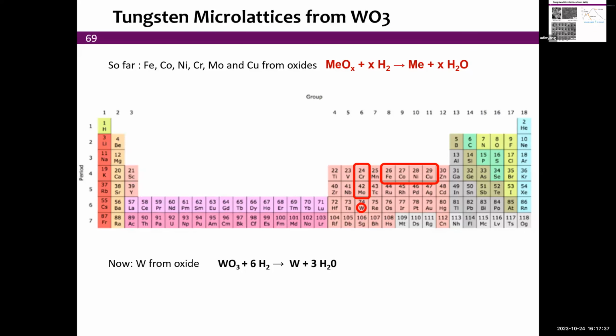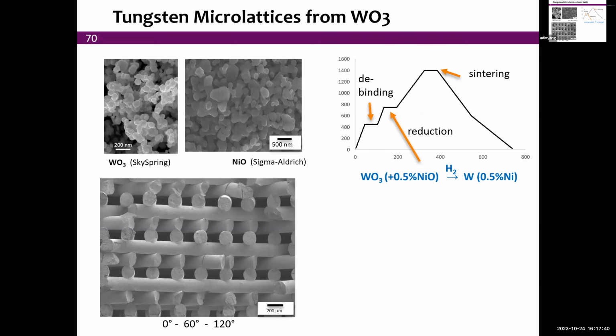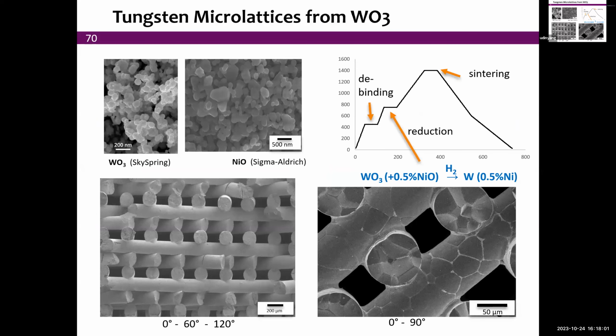So we really wanted to demonstrate tungsten, and it works. I'm going to go a bit faster here. We have tungsten oxide. We add a small amount, about 0.5% of nickel oxide, the reason being that tungsten with nickel sinters much faster than pure tungsten. That's because it creates a transient liquid phase. I'll show you in a second. So here is our printed structure, and here's our reduced and sintered structure. You clearly see the beautiful struts. You see a cross section here, and you clearly see segregation of the liquid phase that dramatically accelerated the sintering.